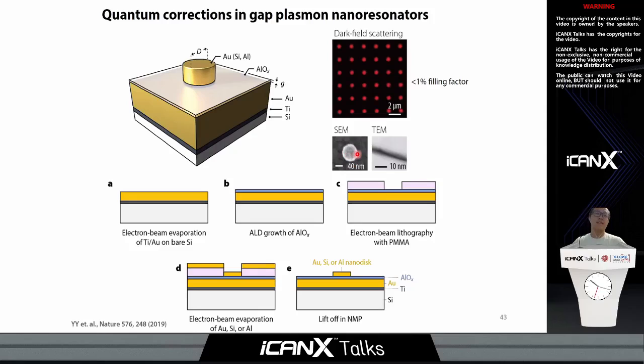And the second question is regarding the radiation efficiency, right? So how lossy these nanoresonators could be. I can tell you that the radiation efficiency of this resonator is quite low because the plasmon is extremely confined within the gap, which is a few nanometers. So the efficiency we obtain is around 1% or even smaller. This is actually the reason why we need to resort to a cluster measurement rather than single particle spectroscopy.